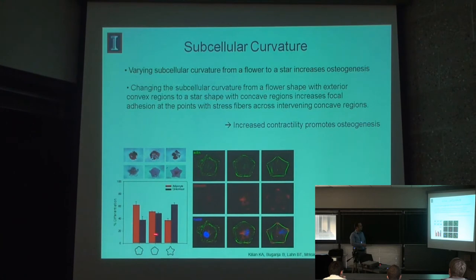When you expose them to the differentiation conditions, we find that going from this flower to a star shape, you see almost a complete lineage shift, where now on the star most cells are differentiating to bone cells. And consistent with the spreading and with the aspect ratio, when we do immunostaining for actin and vinculin for focal adhesions, we see that cells in star geometry have a much higher degree of these bundle-like stress fibers between the points of the star.